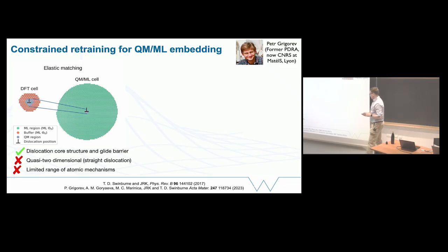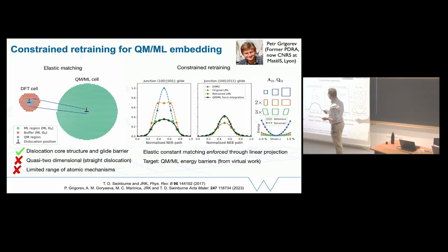So when we did this a few years ago, we looked at the effects of hydrogen and helium on dislocation glide barriers in these narrow 2D cells, and we saw something that we thought was interesting, but we weren't really sure if it was meaningful. We'll come back to that a bit later on. But what we could do is use these quasi-two-dimensional structures to update the machine learning potential that we're using for the outside, for the embedding part, so that it knows how to correctly describe migration of dislocations.